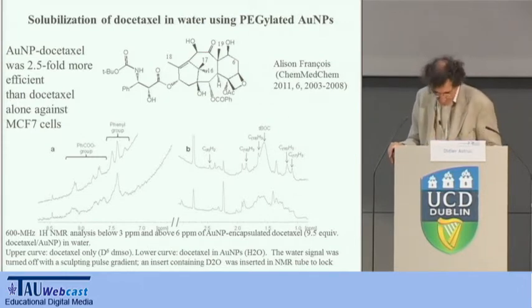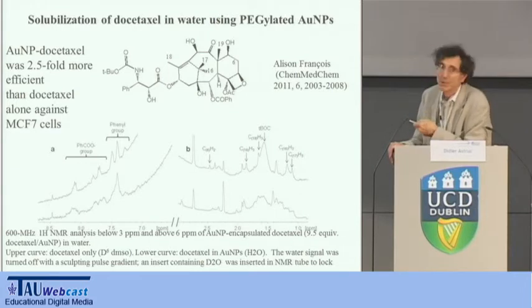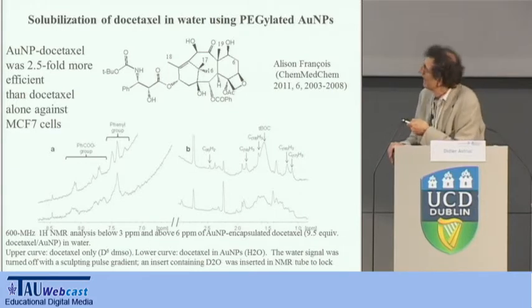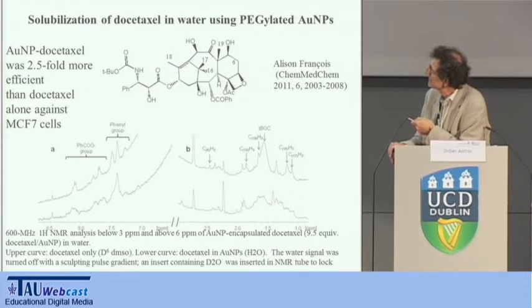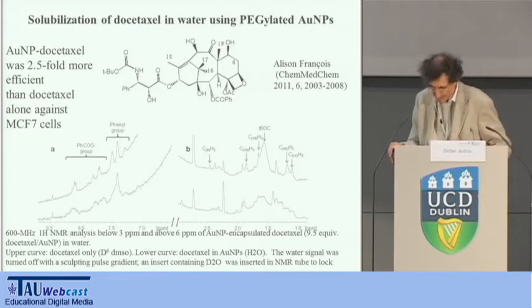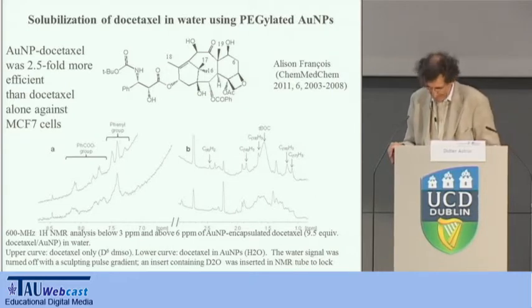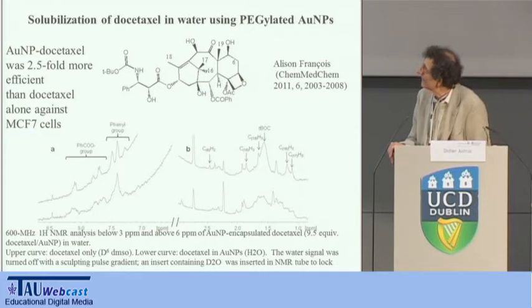Well, these nanoparticles are non-toxic to a normal cell, completely non-toxic, as I already mentioned. But they are toxic for cancer cells. You can see that they are 2.5-fold more toxic than the drug alone. So it means that there is a benefit of encapsulating the drug into this water-soluble nanoparticle, and you have a benefit for attacking the cancer cell with this system.